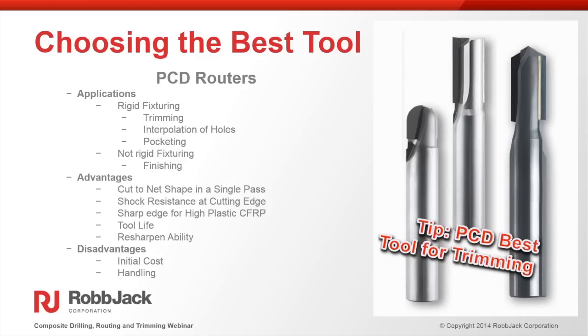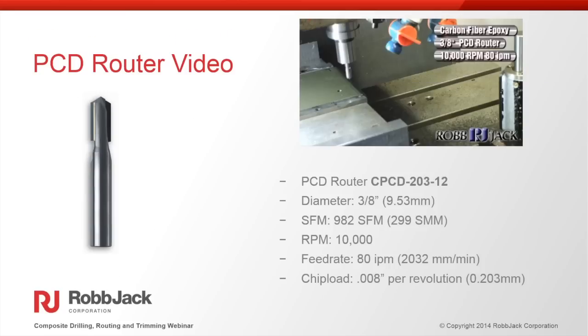And so that saves cycle time and actually reduces the number of linear inches that the tool sees, so it actually gives you longer life. So in this video, it's a 3/8 diameter router, or 9.53 millimeters, and we're going to be going 982 surface feet per minute, which is slower than some of the trimming that I've seen at a lot of places.